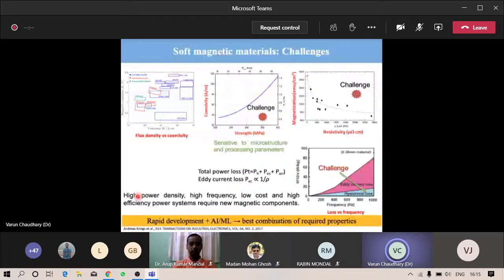So now what are the challenges to achieve those properties? Here, the first window shows the typical magnetic materials performance, the saturation magnetization and the coercivity. A material which has a high value of saturation magnetization also has a high value of coercivity. If you want to decrease the coercivity, the saturation magnetization also decreases. So we need a material which has a high saturation magnetization and a low value of coercivity, somewhere in this region. Another challenge is that when we increase the strength of the material, the coercivity also increases. This is because both coercivity as well as strength are functions of microstructure, and therefore it's very difficult to get a material with high strength and low coercivity.